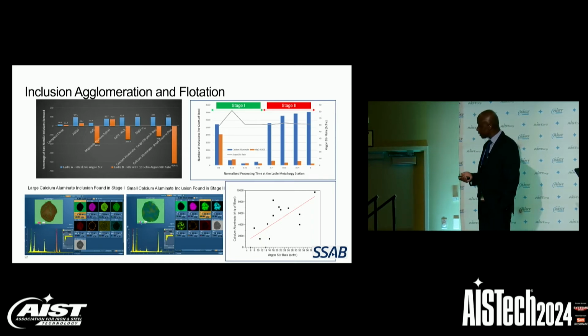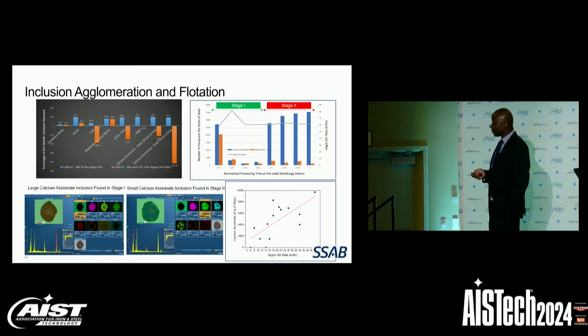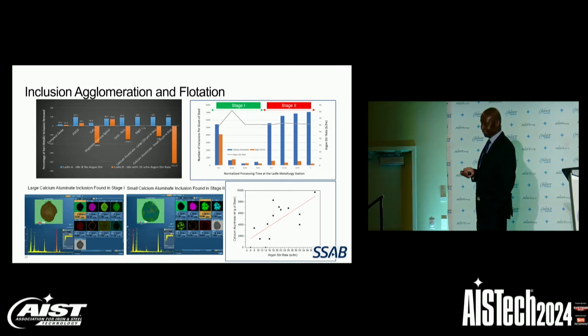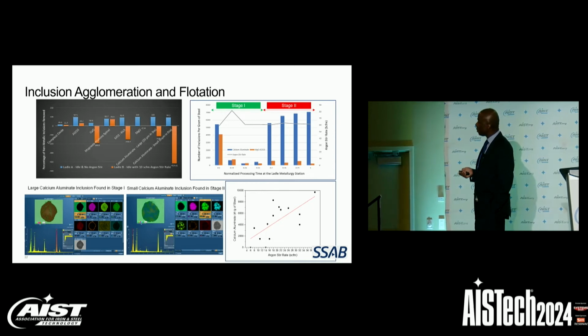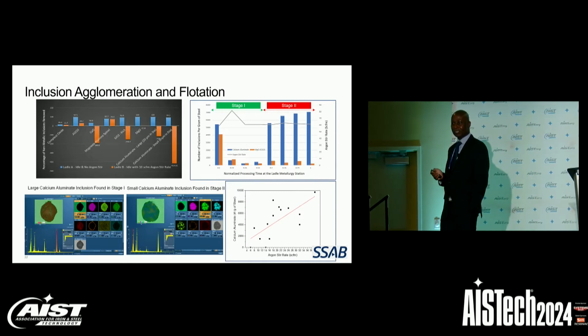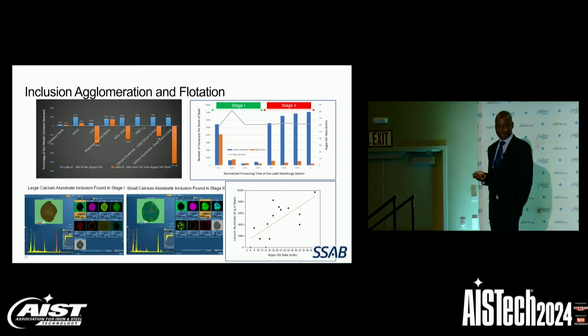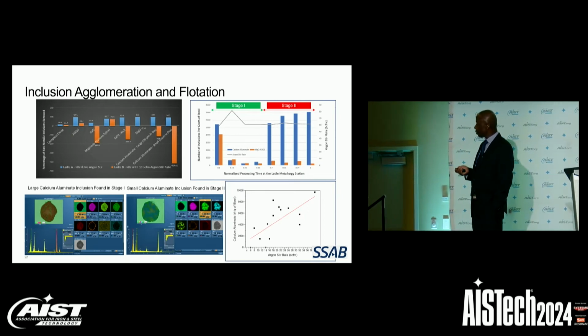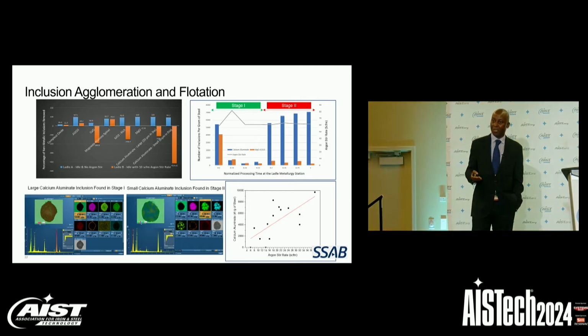And what we found is that the ladle that was idle for 97 minutes with no argon stirring has significant decreases in the population densities of non-metallic inclusions, whereas the ladle that was idle for 57 minutes and stirred at 10 SCFM with argon has significant increases in its inclusion population density. So we concluded that the argon stirring probably perturbed the flotation of non-metallic inclusions from the steel.